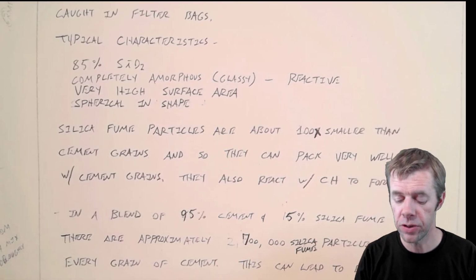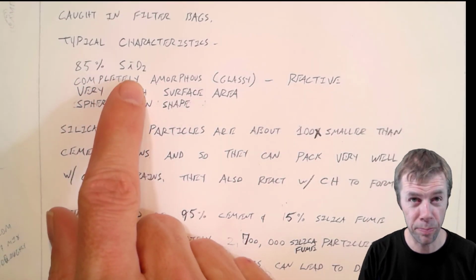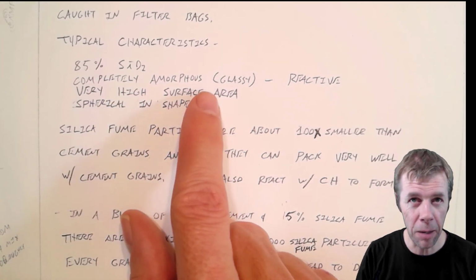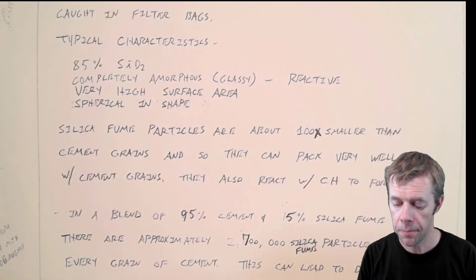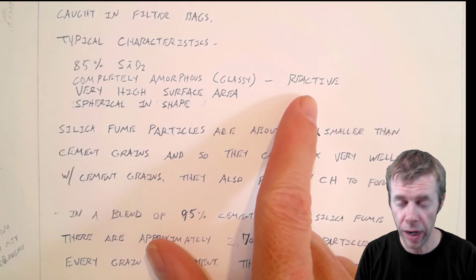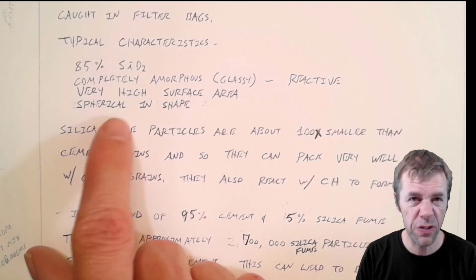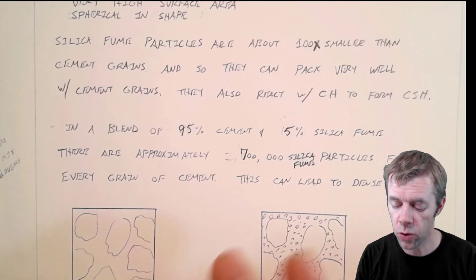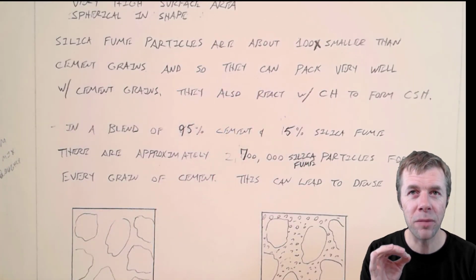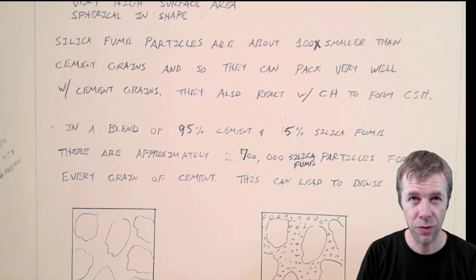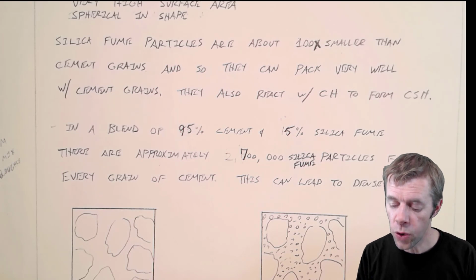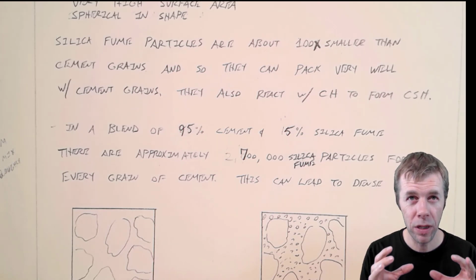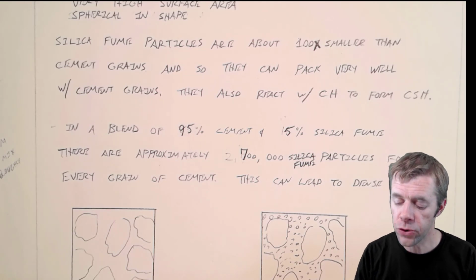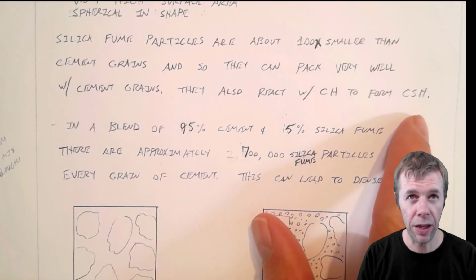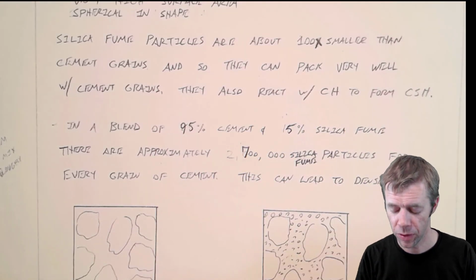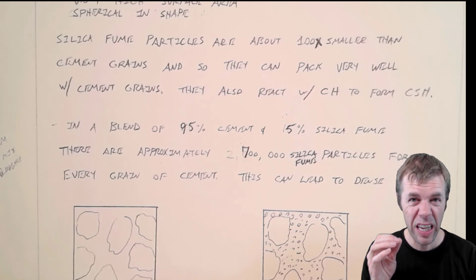Typical characteristics of silica fume is that it's about 85% silicon dioxide, so it's pretty pure. It's almost completely amorphous. That means there's almost no structure to it, okay? So it's extremely reactive. It has a very high surface area, and they're spherical in shape. So silica fume particles are about 100 times smaller than cement grains, 100 times smaller. And so they can pack extremely well with cement grains. And they also react with calcium hydroxide to form more CSH. So you get a lot of benefit out of these things. So this 100 times smaller and this packing is a huge deal.